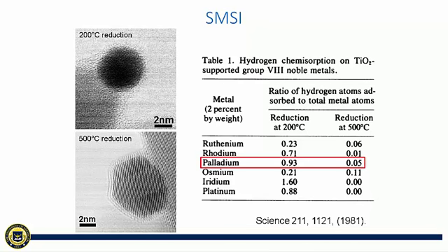Now we want to correlate the structure with the chemisorption capability. The amorphous layer corresponds to the state produced by low temperature reduction, where we can see most of the metal sites are still active in adsorbing gas molecules, indicating the amorphous layer is gas permeable, while the crystalline bilayer corresponds to the state produced by high temperature reduction, where almost all the metal particles cannot adsorb gas molecules anymore, indicating the crystalline bilayer is very effective in blocking the access of gas molecules.